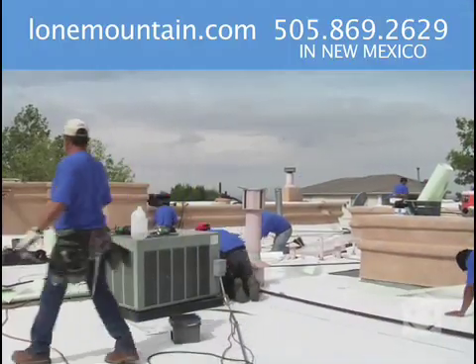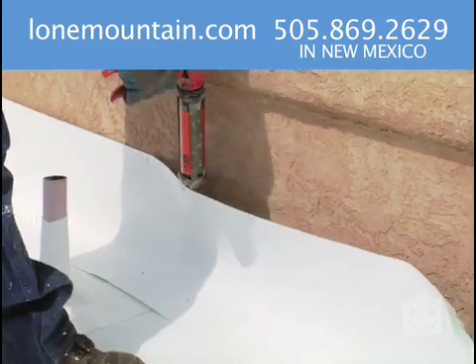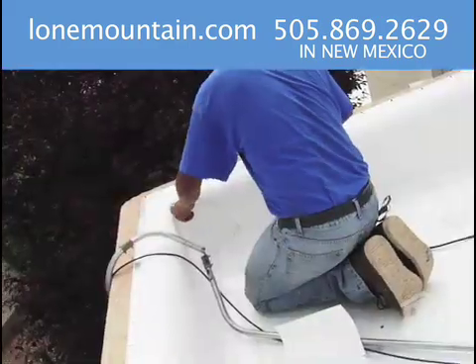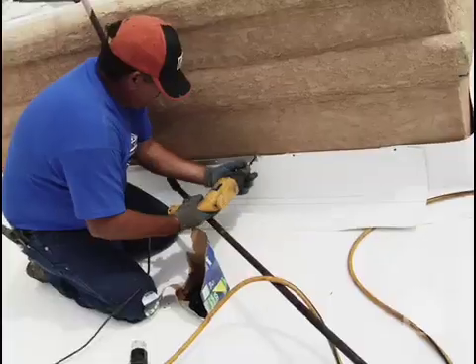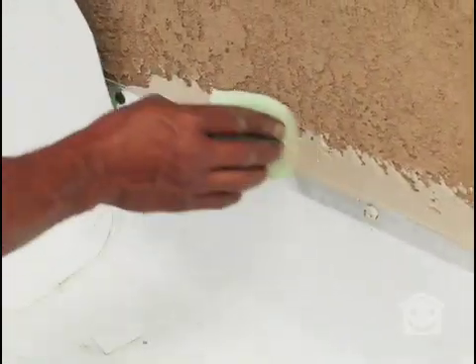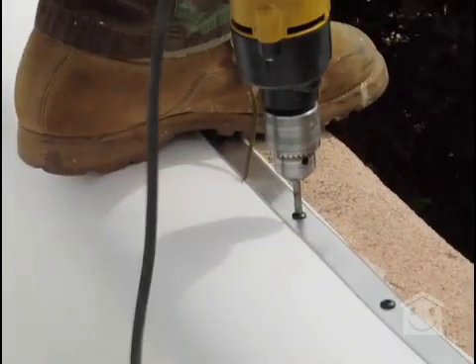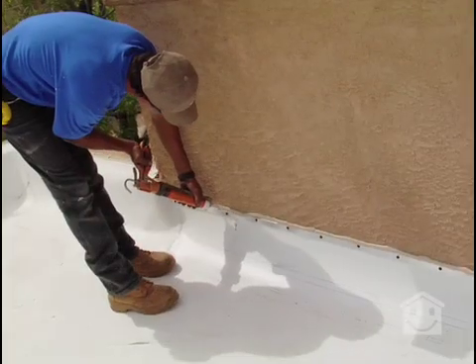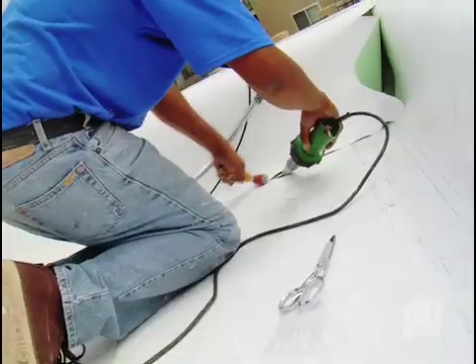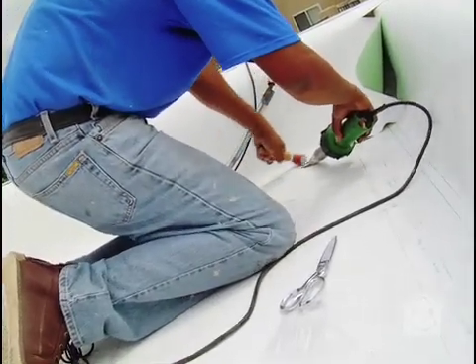Once the main flat roof area is covered with our Pro-Ply, we turn our attention to the parapet walls. These are one of the main problem areas on a flat roof, especially where the walls connect to the roof itself. What we do is bring the membrane up approximately 18 inches or more on the parapet, and in some cases we go right up and over the top of the parapet. The parapet membrane is fastened to the structure, terminated and sealed, and of course we fuse the membrane to itself so we can create a single solid seal on the roof with no possibility of leaks.